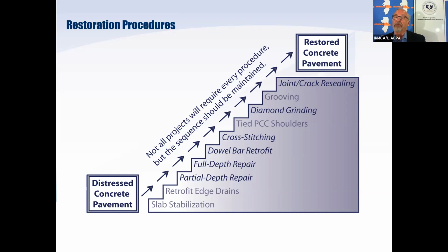Dowel bar retrofit, if you have a lack of load transfer at transverse joints, we might want to come back and install dowel bars to effectively increase the longevity of the pavement. Cross stitching, if you have a longitudinal crack in the pavement and you want to completely immobilize it, cross stitching or slot stitching is certainly an appropriate technique. And then finally, we get up to joint and crack resealing. Every pavement responds to moisture in a negative way. So one way to prevent moisture from intruding into the pavement from the top down is to simply seal or reseal joints and cracks that have developed in the pavement.